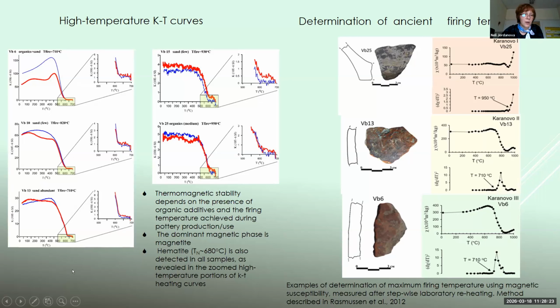And it was also found that samples which contained more sand additions display almost reversible thermomagnetic curves, while samples containing organics addition except sand display non-reversible behavior.